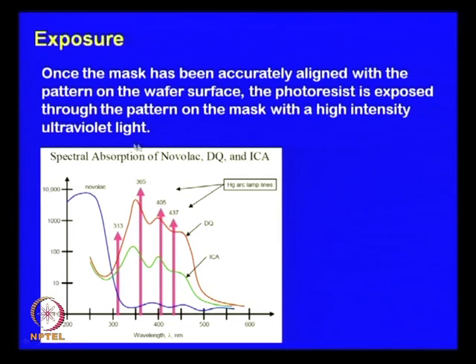Now, if you look at the spectral absorption of a typical photoresist, this is the type of absorption peak you will see, that it absorbs light corresponding to UV wavelength. Here you see in the visible range the absorption is nearly 0, but still there is a bit of absorption between 400 and 500.